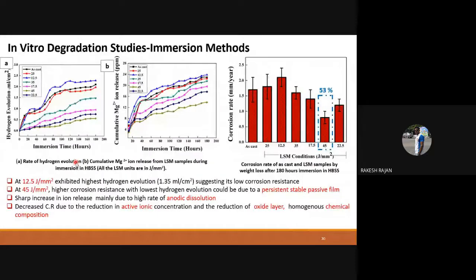And this is the in vitro degradation studies after laser surface melting. You can see the same kind of hydrogen evolution investigated through 180 hours of immersion of the sample. And even magnesium ion release, the trend of the graph shows a very minimal rate of degradation happening for this curve. That means this is an ideal candidate for bioimplant application with controlled degradation.